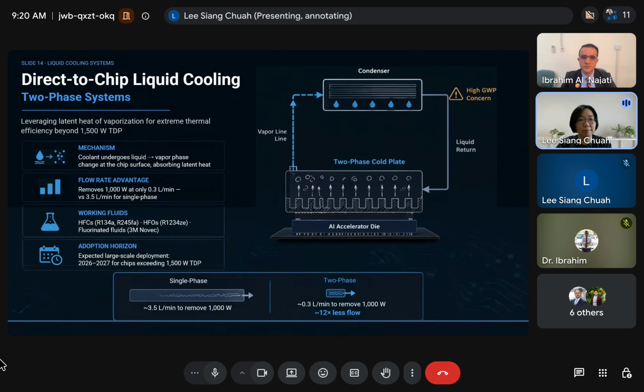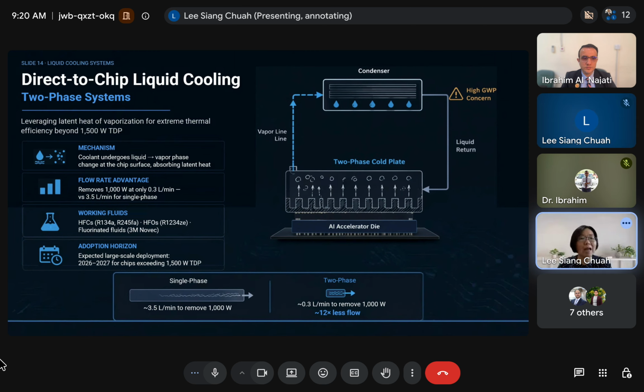Okay, two-phase cooling is a fundamental shift in thermal management and will define the next generation of AI cooling. Unlike single-phase systems, the coolant in two-phase cooling boils at the surface, undergoing a liquid-to-vapor phase change. This leverages the latent heat of vaporization, allowing much higher heat removal efficiency. The impact is significant. To remove 1,000 watts, a single-phase system may need about 3.5 L/min of flow. So we can see that two-phase cooling achieves higher performance by using the fluid itself as the heat transport mechanism.